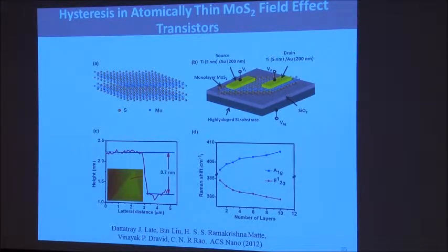You can see how many layers you have by using Raman spectroscopy, looking at the A1G band and the E1-2G band. As I told you, the A1G band softens and the E1-2G band stiffens as you decrease the number of layers, so you can identify a single layer or a two-layer MoS2.